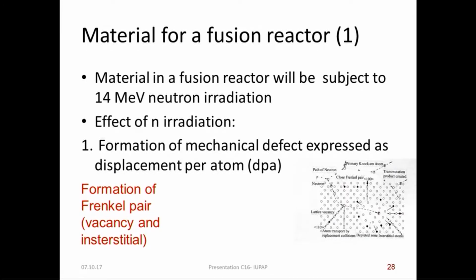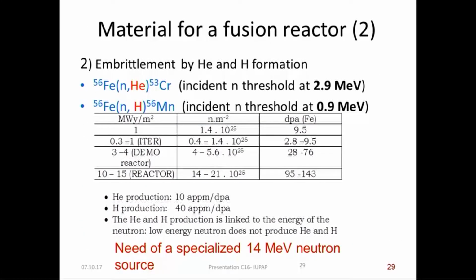Now, I would like to share with you a few concepts about the materials. When a material is hit by the 14 MeV neutrons, there will be formation of Frenkel pairs, which will have an effect on the mechanical properties. The second point is that you have embrittlement by helium and hydrogen formation through the two reactions with iron, which is on the screen. So we have here a very delicate balance between the hydrogen and helium production and the mechanical defects due to the Frenkel pairs that I have mentioned to you. We have, for example, about 10 appm of helium production per mechanical damage, as I described before. So we need a specialized 14 MeV neutron source.